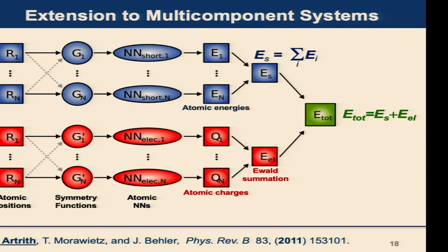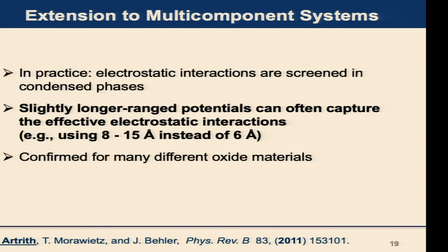I already explained this before, and in this term we include the electrostatic term, which, for example, is obtained from Ewald summation. After some applications, we found that the second method I just explained works very well for multicomponent systems. In practice, we found that the electrostatic interaction is actually already screened in the condensed phases. We also tested and checked the output. So we found that actually